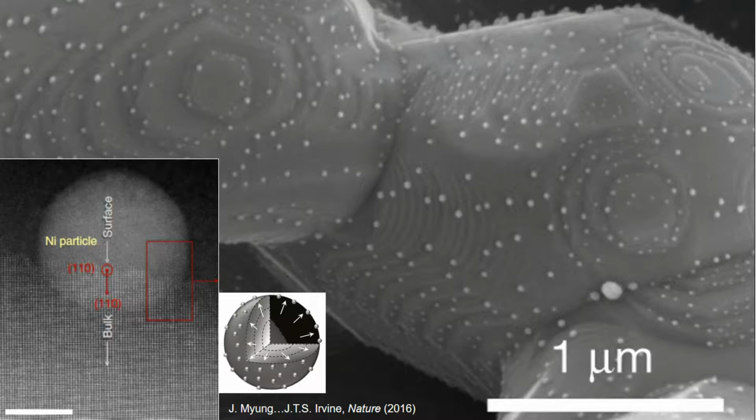Recently, it was shown that several oxygen reduction catalysts undergo the process of metal exsolution, where metal cations diffuse to the oxide's surface to form anchored catalytic nanoparticles. These anchored nanoparticles have superior durability without sacrificing activity at service temperatures. However, the exsolution mechanism is unclear, and new exsolution-compatible compositions are regularly reported, so room exists to develop optimized catalysts.